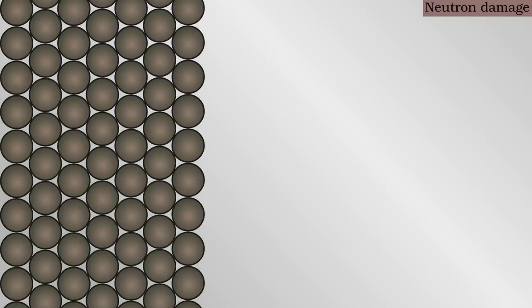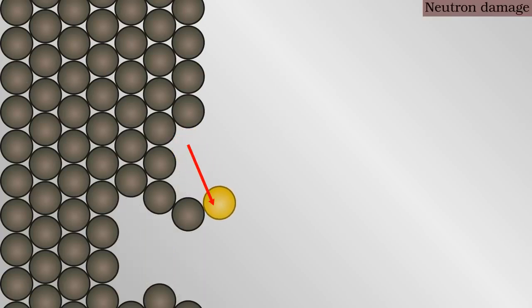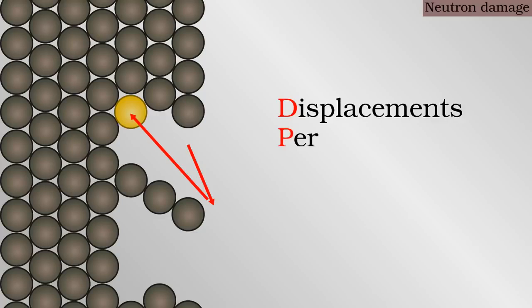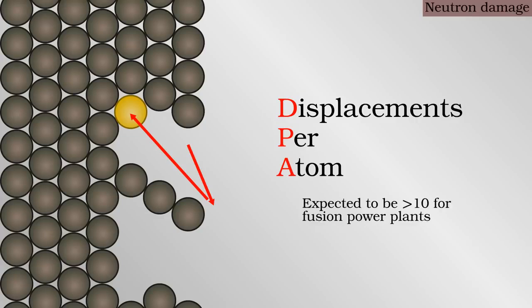A fusion reactor, on the other hand, must have a solid first wall, as I discussed previously. Atoms in such a material are formed into a lattice or similar arrangement, which does not take kindly to being treated as a pool table. If a given lattice atom receives anything more than a small threshold amount of energy, it will settle away from its starting location. Gaps will open up in the material, it will become brittle and swell in size. Gas builds up in the cracks and voids, further stressing the material. Neutron damage is quantified by a metric called displacements per atom, or dPa for short. For the first wall and similar components, this number may become greater than 1, and even in the tens and hundreds. Needless to say, this many displacements is bad news for an otherwise ordered solid material.